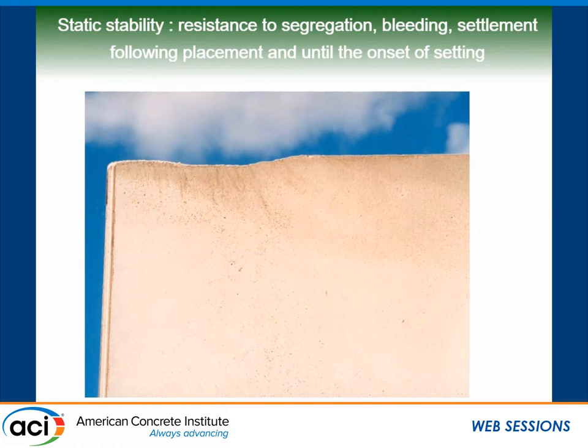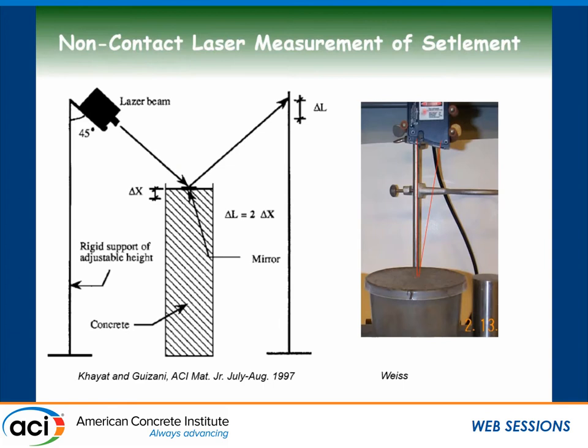So how do we measure, how do we evaluate surface settlement? Here you have one approach. This is the approach that we used many years ago, and the slide is very old. But basically you have a fresh concrete column, and then you put a very thin small mirror, and you shoot a laser beam, and from the deflection of that laser beam, you can evaluate the settlement of the surface. And later on, the group of Jason Weiss at Purdue University developed a very similar test, where they also have a laser and detect the surface settlement. So that's one approach to evaluate surface settlement.